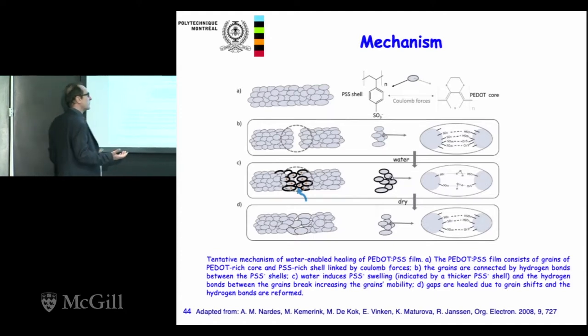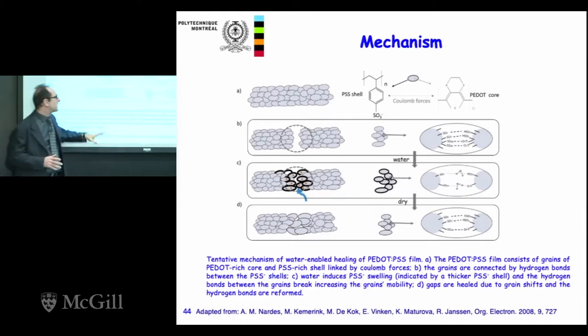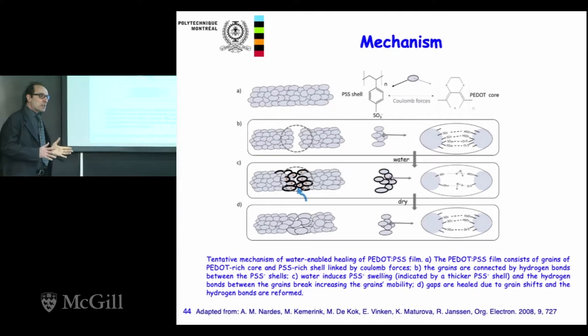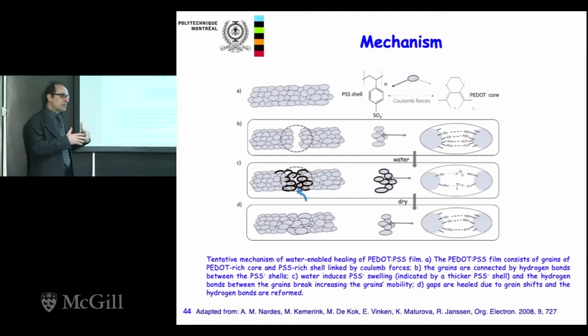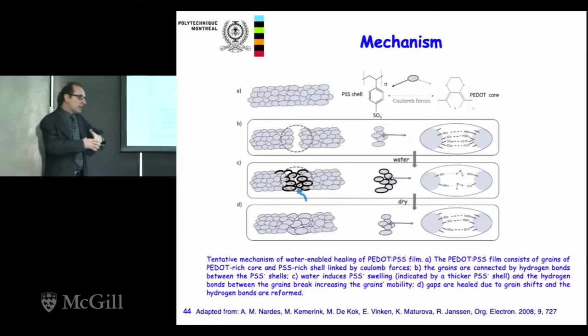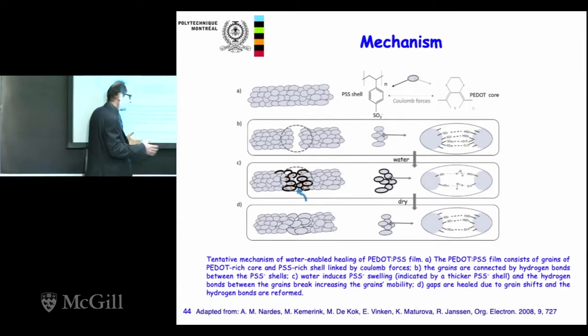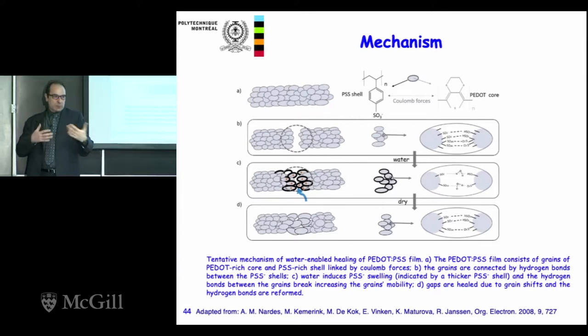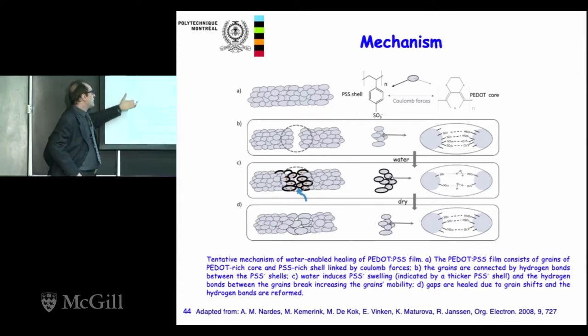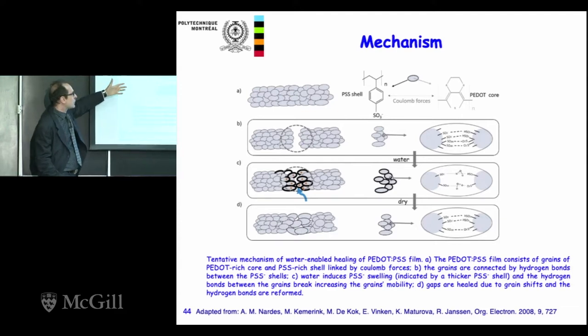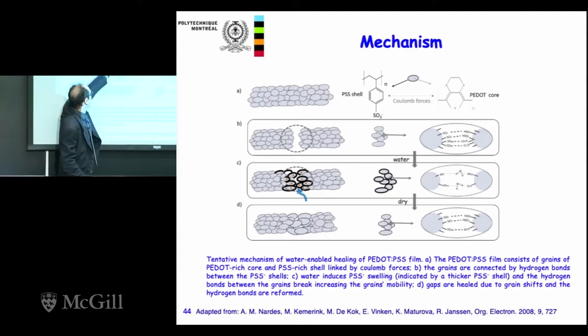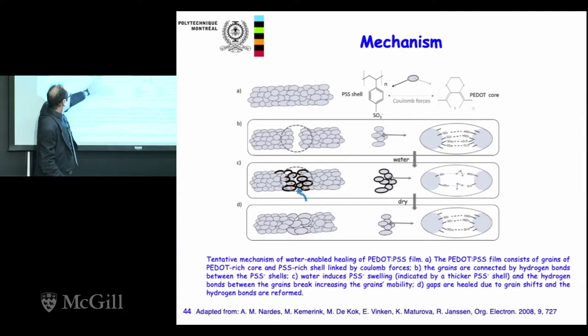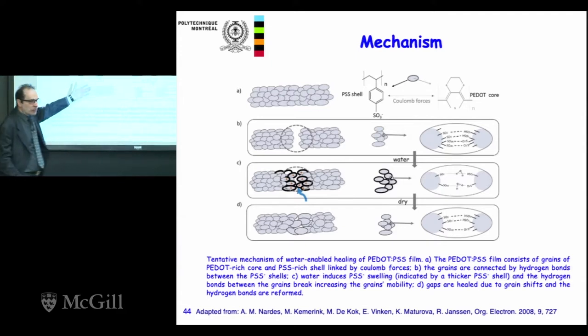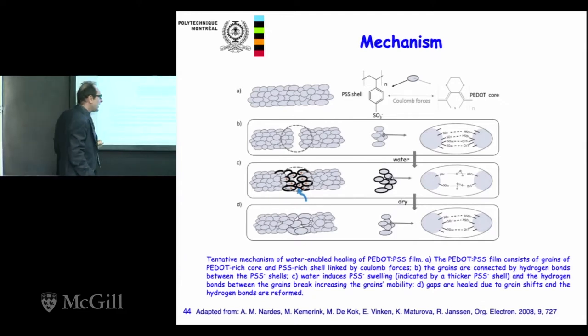Then what about the mechanism? We are still trying to understand the mechanism. We believe that it's related to the swelling. So these materials are very well known for swelling. They can increase up to 3 or 4 times their weight if they're immersed in water. And we believe this is associated to the increase of volume also. So what could happen is that you have two separated parts. You put them in water, they swell, then they end up touching. This is just something we suppose. It's not even clear. We have to prove this mechanism.